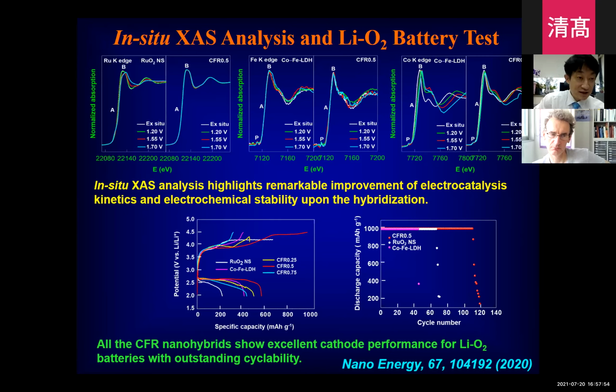To understand the advantageous effect of hybridization, we did in situ XAS analysis during the electrocatalytic reaction. As you can see here, in the case of ruthenium oxide, the application of electrical potential induced the migration of the absorption edges due to charge accumulation. But in the case of the hybrid material, there's no significant change of the edge, due to the efficient charge transfer in the intimately coupled nanosheet. Also, in the case of iron LDH and cobalt LDH, compared with the pristine LDH material, we observed a much weaker change of the edge, due to the efficient electron injection into the reactant. So here's the evidence for the enhanced interfacial charge transfer between the catalyst and the reactant materials.